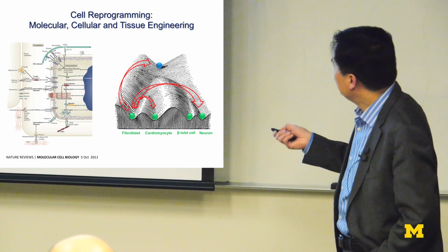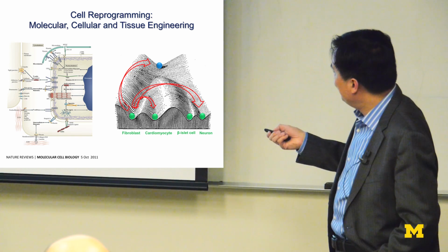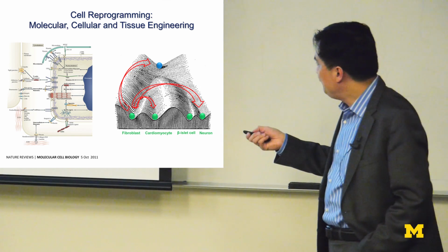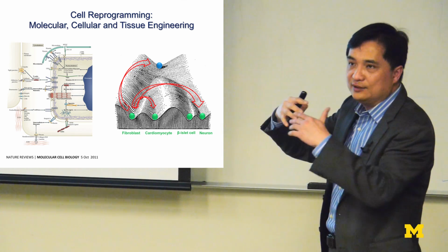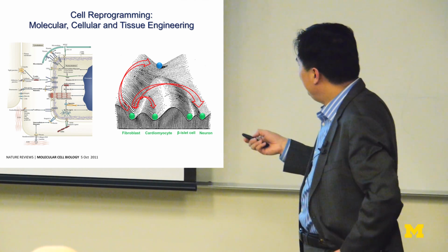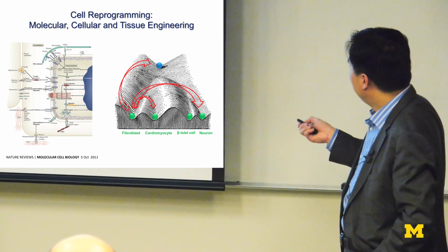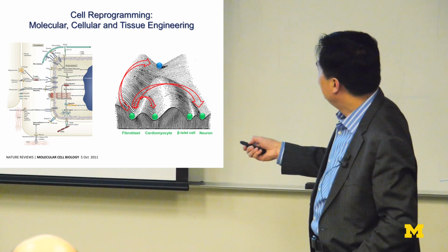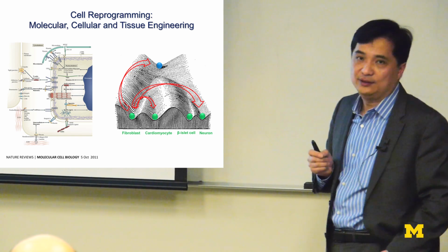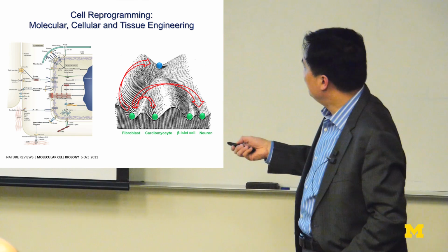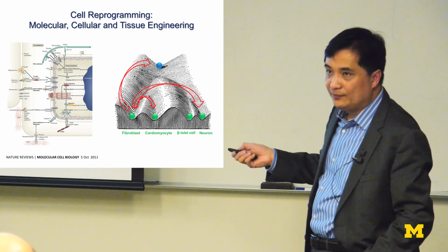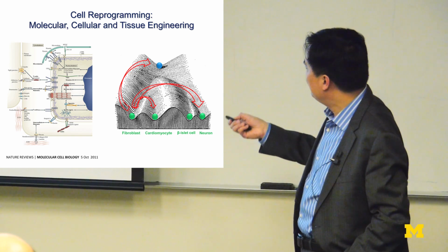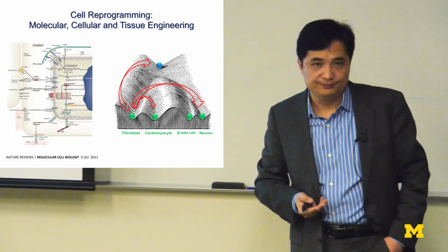So I also want to mention, besides our finding on the fibroblast reprogramming into pluripotent stem cells, we also found that if you have a certain kind of substrate with different stiffness, you could regulate the fibroblast reprogramming into neurons. So this is a direct reprogramming process. That means the biophysical factors indeed could move the cells along this epigenetic landscape, change the epigenetic state, and make the cell reprogramming into pluripotent stem cells and other specific cell types easier. So that's what we found.